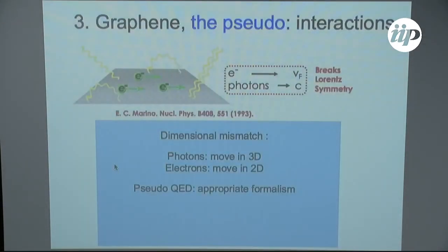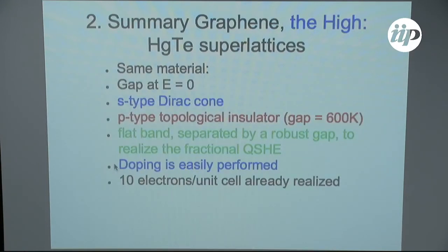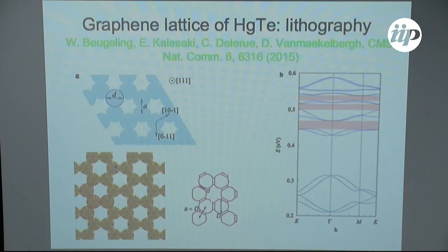So these were, yes? Yeah, so in this one, we have been doing several studies, all the values. If you look at the paper, you will see if you change the values of D compared to A. Here, my A is 1.02 D, and the D is 7 nanometers, okay? So it is all below 10 nanometers in that range. But we look at several values, and we show how the gap varies as a function of these ratios, and also as a function of the truncation. The truncation is very important because you want to connect via many atoms, okay?